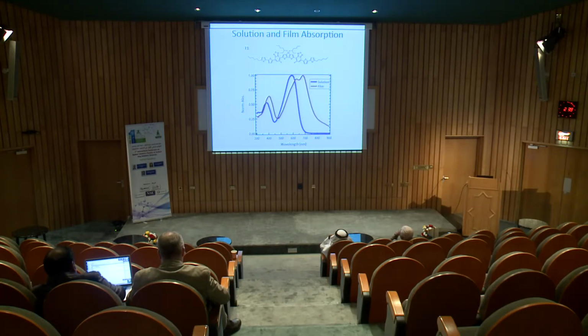It was first made by Guy Bazan in 2011. You can see here the absorption of the p-DTS(FBTTh2)2 molecule. The blue one is the absorption in solution, and the red curve is the absorption in the film. When you go from solution to the film, when there is no more solvent, the molecules have a strong interaction between molecules, and you can see the absorption actually broadens, and you see a vibronic structure appear, the peak that appears on the right-hand side of that plot. And usually that is a signature of a very ordered film.